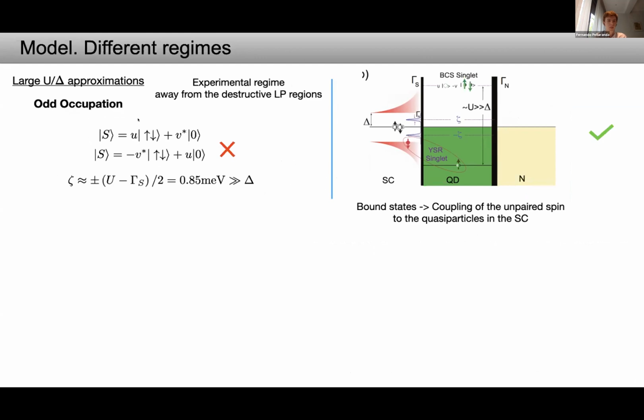So in this case, the singlets are not formed by mixing of occupations of doubly and empty occupied states, as was the case before, since these states would lie well above the gap due to the large charging energy. What we have instead are bound states formed by the coupling of the unpaired spin to the quasiparticles in the superconductor.